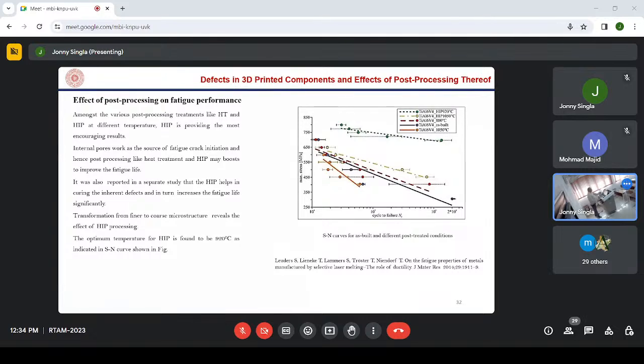Now this is the effect of post-processing on fatigue performance. So if you see this green line, this is basically the S-N curve for high cycle fatigue. Here we have the stress level, that is how much stress you are putting on the component. Here, number of cycles to failure. So if you see this line, this corresponds to HIP treatment, right? If you compare this with as-built, it is this line. So there is a big gap.